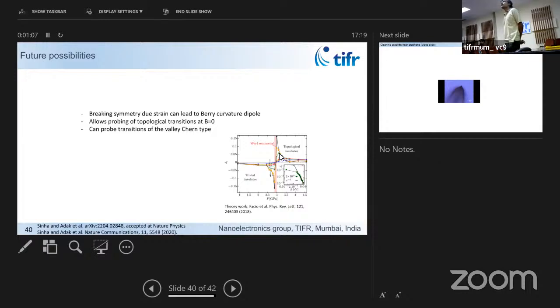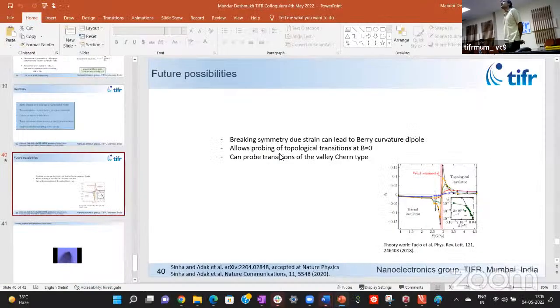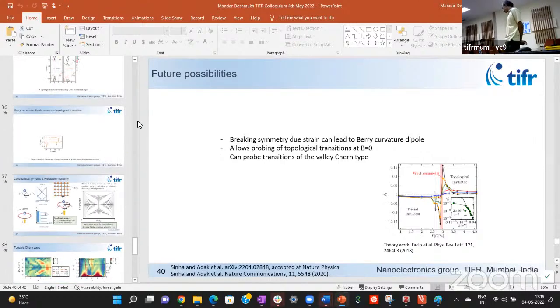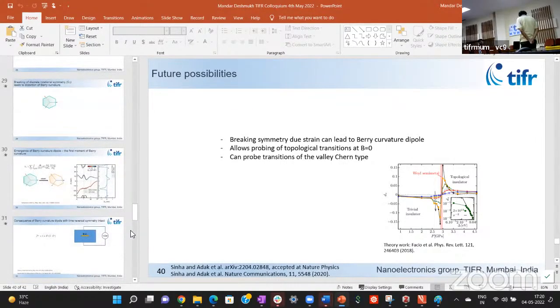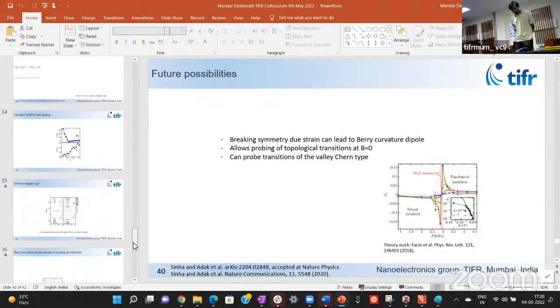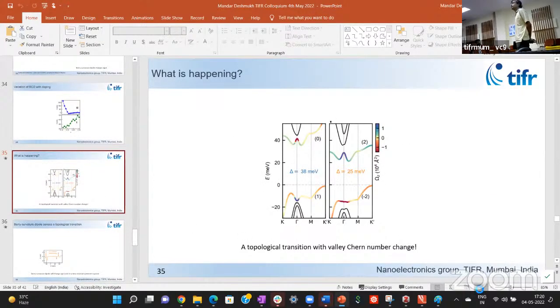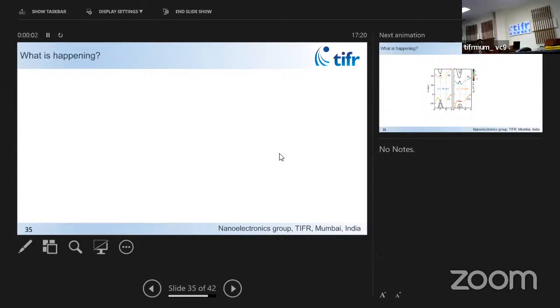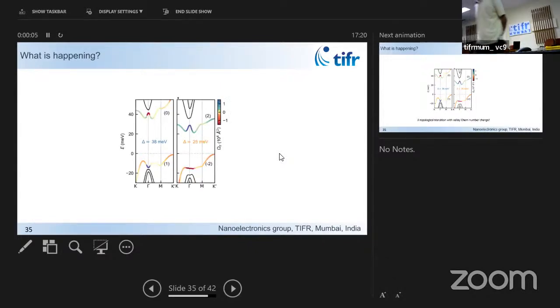I mean, it's connected to this idea of band inversion. When you have a topological transition in the picture that I showed you, there's a band touching, which flips the sign of the Berry curvature, and that also automatically gets reflected in the Berry curvature dipole. So as a function of the electric field, what has happened here is when these are on either sides of the topological transition, the flat band touches the remote bands. It exchanges the Berry curvature, and the Chern number changes, the Berry curvature changes, the Berry curvature dipole also changes. So it's a very general idea.